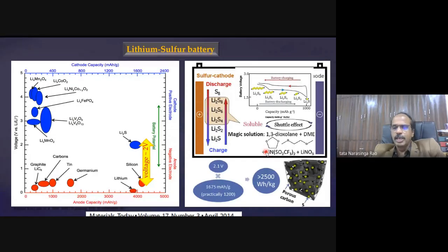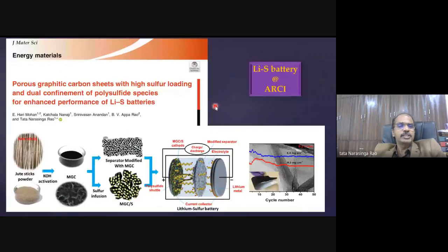So can I do that? Can I increase its cycle life by containing these polysulfides without going into the electrolyte? If you have sulfur in a carbon matrix, like here you can see porous carbon, and the yellow particles are sulfur, and you embed sulfur into the porous carbon, which is conducting, and use that as an electrode, then the polysulfide that is formed gets trapped within the pores and doesn't escape into the electrolyte. So that is one of the strategies.